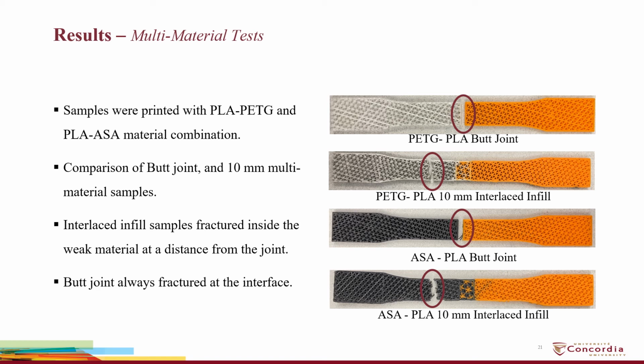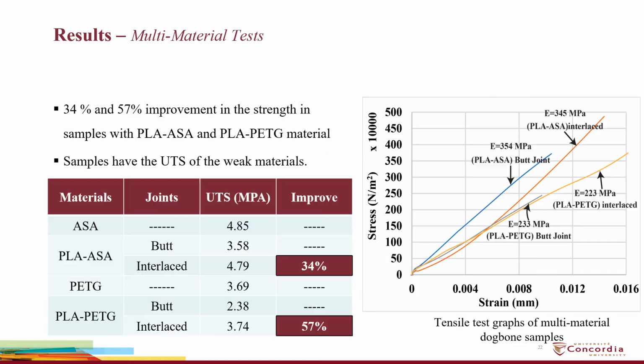Actually, the samples fractured in the weak material infill, which shows that interfacial joint is as strong as weaker material region. Moving on, for the samples with PLA-ASA material combination, we observed 34% improvement. And for the samples with PLA-PETG material combination, we observed 57% improvement in mechanical strength. This shows that interlacing has more impact in case of weaker materials.